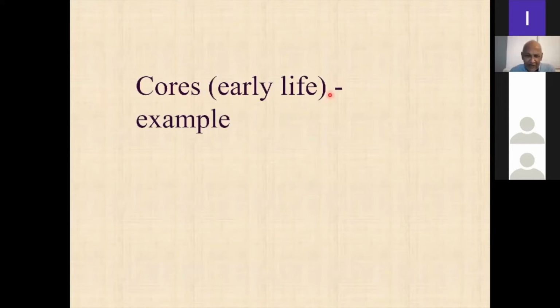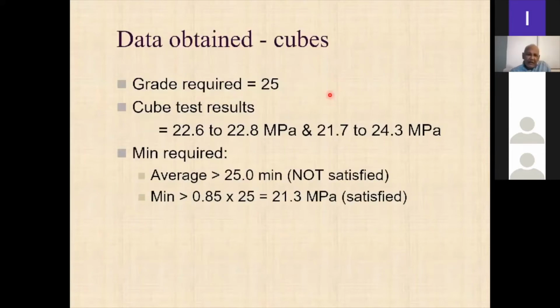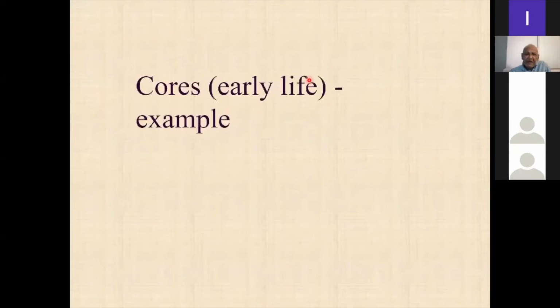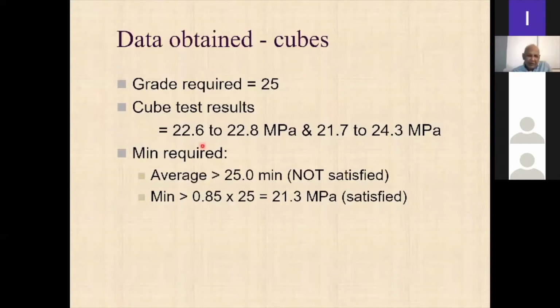Right. So now this is the data obtained. This is the first example, cores taken from early life. Let us say the grade required is 25. The cube test results you have got are only this: 22.6 to 22.8 MPa and 21.7 to 24.3 MPa, two sets of results for some reason. I can't remember that now. Anyway, even for a small supply of concrete, your average must be greater than 25, right?